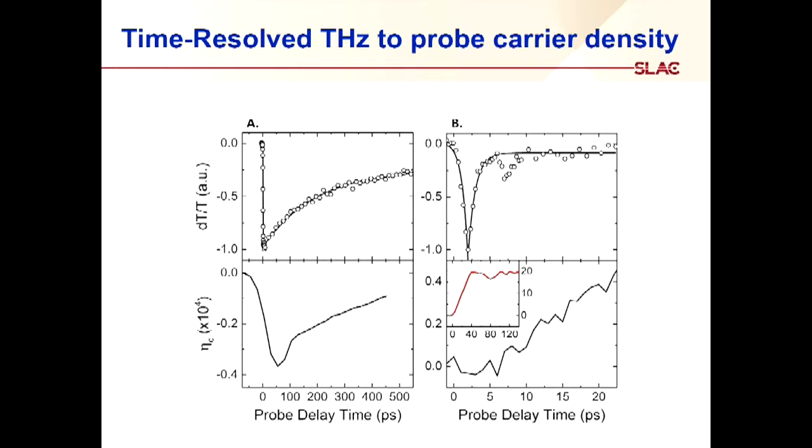And this is the kind of correlation we saw in two different materials. This was in moly disulfide. This was in rhenium disulfide. So if this is the terahertz response, and we create a lot of carriers, the carriers screen out the field. We see a decrease in the terahertz transmission. And in the case of moly disulfide, like the purely optical experiments I showed you earlier, we get a recovery of the carrier density over a pretty slow timescale, hundreds of picoseconds here. So